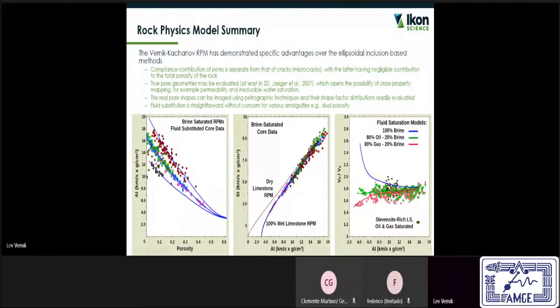Another confirmation of what I mentioned about the sensitivity of tight carbonates to fluids can be visualized on this plot, which is my favorite in fact, acoustic versus shear impedance. So all of these limestones and carbonates and dolomites are brine saturated here, and the dotted line is a dry limestone line. And you can see that only at relatively low impedances or high porosities, like in chalks, like in Denmark, for instance, you stand a very good chance of using AVO and seismic inversion, simultaneous two-step inversion, to separate the gas versus brine versus oil in place.